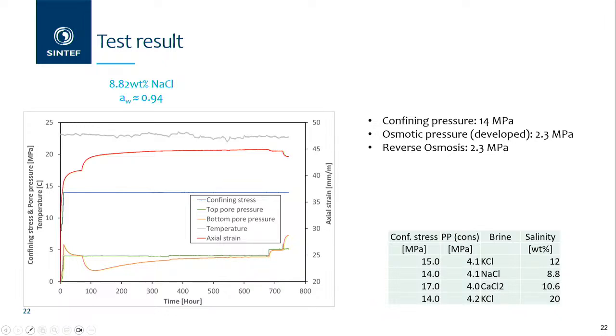The pressure is hydrostatic pressure from all sides. What is the pressure here? Yeah, 14 megapascal, 140 bar, and the pore pressure, the sample and the fluid on the top, is exactly the same pressure. The difference is the ionic concentration. The sample has 3.5% sodium chloride. The exposed fluid that I measured with is sodium chloride, 8.8%, and calcium chloride, potassium chloride. The difference is in concentration, but the activity is the same. So I keep the activity because the osmotic pressure depends on the activity, not the concentration.